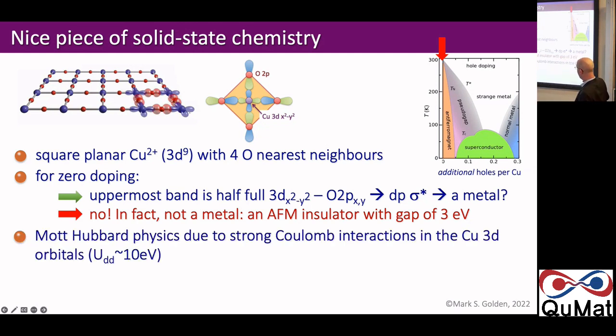Okay, so there's strong Mott-Hubbard physics due to the Coulomb interactions between the copper 3d electrons. So you have a lower Hubbard band down here, upper Hubbard band up there. This is about 10 eV, even after screening in the solid state. And the gap that you see in these cuprates, if you have energy going up to the right, is because in between these two Hubbard bands are the oxygen 2p states. So the gap is actually a charge transfer excitation from the oxygen 2p to the upper Hubbard band copper 3d. So in the language of Jan Zaanen's PhD, U is greater than delta, so these are charge transfer insulators.